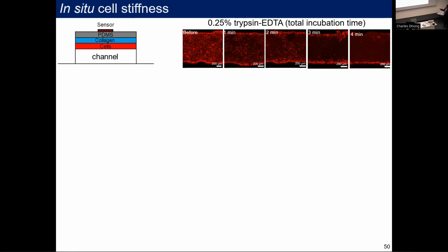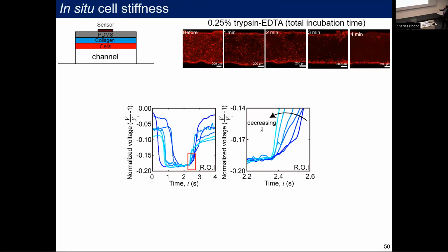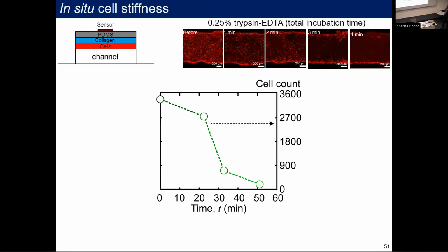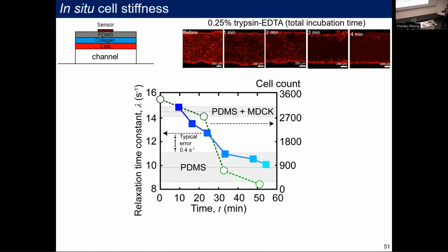So what we can do is put in trypsin EDTA, basically dissolve the cells. And this is what happens visually, where you can see lots of individual cells here, and then over time, there are fewer cells. And so we can just flow a bubble all throughout this, right? And start to see this decreasing relaxation time. On the right here, we have the cell count, which I can just get from counting these. But on the left here, this is the actual viscoelastic constant of that layer in real time.